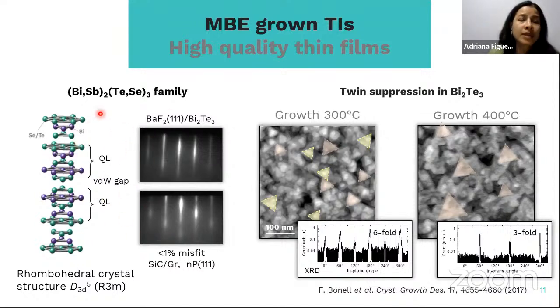So we grow these materials, which we call van der Waals materials because they grow in a layered feature. They are characterized by a basic unit, which we call the quintuple layer. Each quintuple layer is formed by 5 layers, 3 of them of the chalcogen atom and 2 of them of bismuth or antimony. These are bonded to the other basic unit, the other quintuple layer, by van der Waals forces. So we end up with a layered system, or van der Waals system.